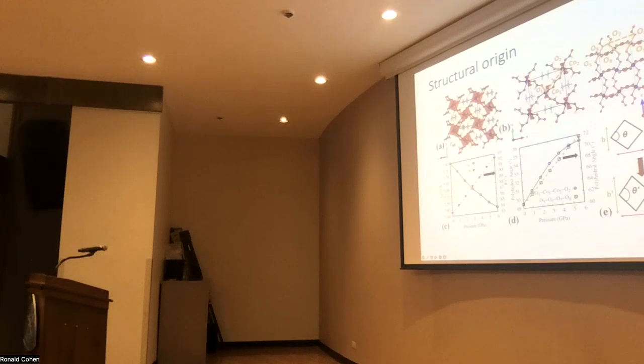And what happens in this case is illustrated in the schematics. If we increase the hinge angle, you can see we can increase the B lattice parameter. And this is exactly what happens here. So this hinge angle turns out to be rather flexible, which again we can trace to the tilt of the oxygen octahedra here.